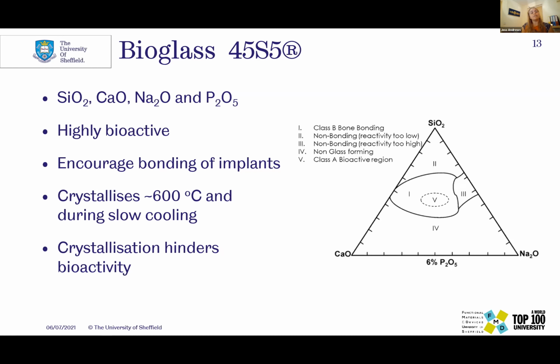There are issues though. It crystallizes readily at 600 degrees and during slow cooling, which means that most of our conventional sort of processing and coating temperatures would potentially increase crystallization. And that crystallization has been shown to hinder the bioactivity, so it would reduce how well implants and things like that bond in the body.